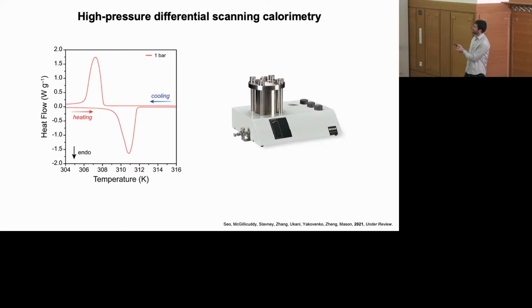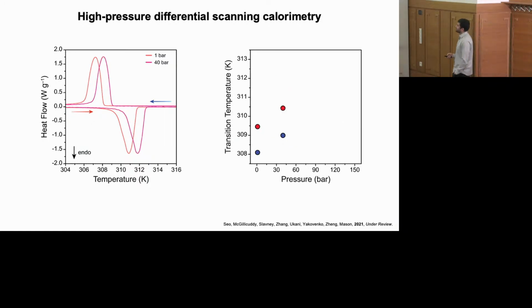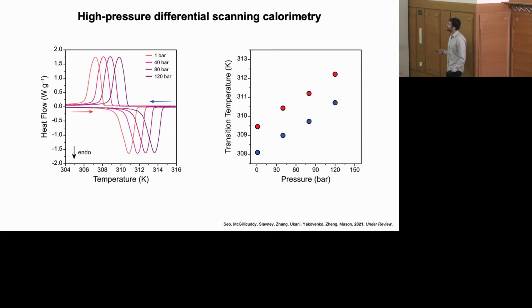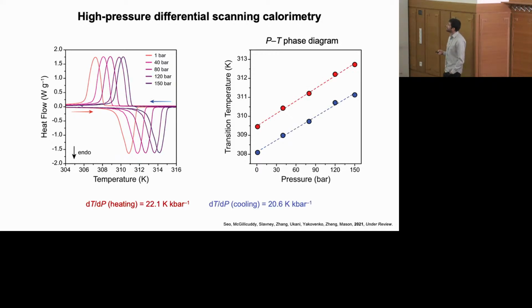So at ambient pressure, as we heat our material and we start to induce the transition, we see a negative heat flow signal that's associated with an endothermic transition. So this is like the solid state melting transition going to the more disordered phase. And then upon cooling, we see an exothermic transition associated with the reverse transition back to the more ordered phase. And so we can start evaluating these phase transitions as we start increasing pressure and going to higher and higher pressures. And we see that the phase transition shifts in temperature much as we expected based on our prediction using the Clausius-Clapeyron equation.